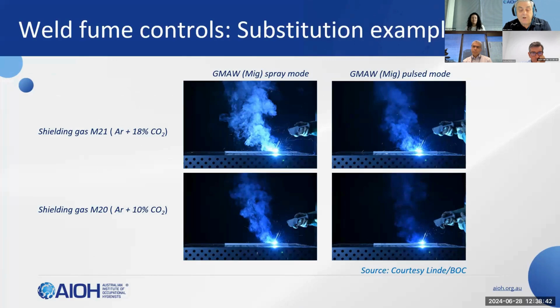Now, this option is typically available in the better quality inverter power sources, particularly for the gas metal arc or MIG welding, where waveform controls such as controlled dip, which includes variants marketed under a range of names, some of you may know them, CMT is one, LSC, RMD, or probably STT is the one that's best known. Or in the higher current process, it's generally known as pulsed welding. And this can reduce the fume generated by up to 70%. Now, if we look at the top two photos in this slide, you can see the effect very clearly with conventional spray mode welding on the left and pulsed mode welding on the right.